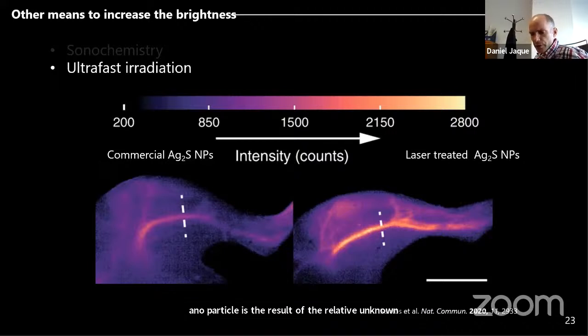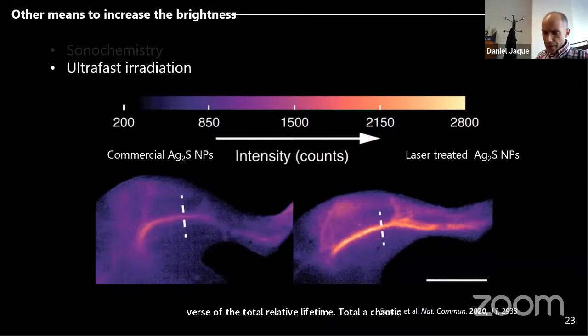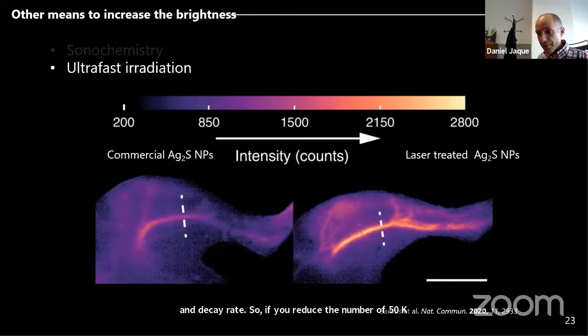So if you reduce the non-radiative decay rates, then you obtain a longer lifetime, okay? Because the lifetime is the inverse of the total decay rate. So if you reduce the non-radiative decay rate, the fluorescent lifetime increases. That's why when you sonicate the nanoparticles, the lifetime increases, because you are removing non-radiative processes, okay?